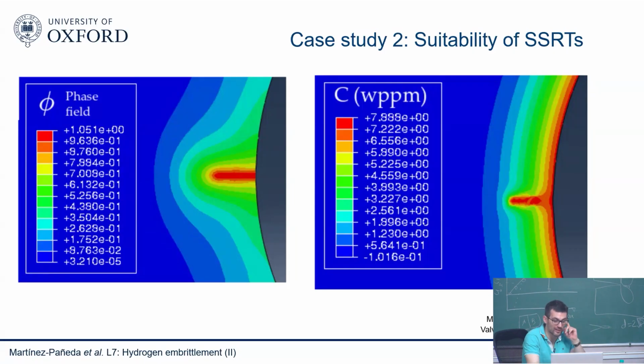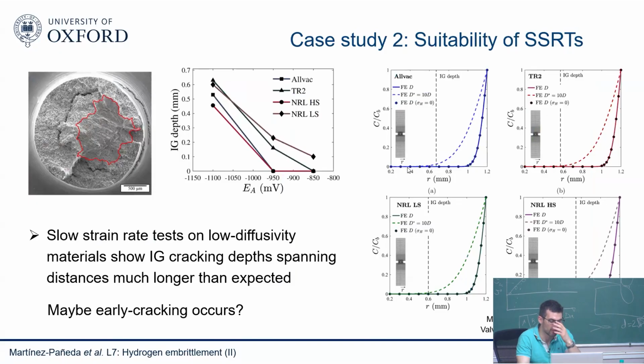This is what actually worries them, because they say, okay, how can it be? If you look at the diffusion, this is over the full time of the test. This is the hydrogen depth. So very little hydrogen came in. Only the surface has hydrogen, but they see embrittlement regions in the intergranular depths that are very, very large. So this is what puzzles them, because these SSRTs are used for all materials. For high diffusivity materials, ferritic steels, within the time of the test you do get quite widespread.